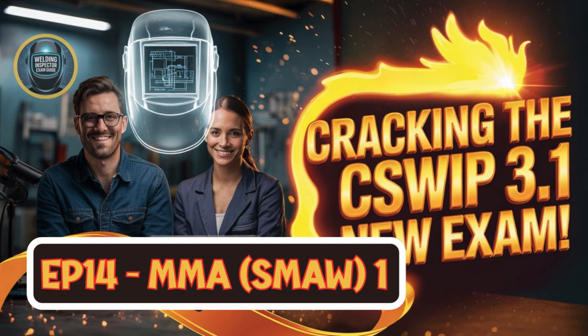Wow, only that much. What happens the rest of the time? The rest of the time is spent on all those necessary but non-welding activities. Stopping to change electrodes every few minutes, chipping off that solidified slag after each pass, maybe grinding out little imperfections or preparing for the next pass, repositioning themselves, repositioning the workpiece. It all adds up. And how does that compare to other processes? Well, you compare that to semi-automatic processes like MIG-MAG or gas metal arc welding. There, the wire feeds continuously. There's often less slag or none. The operating factor can easily be 50%, 60%, even higher in some setups. Double the arc time. Easily double. And then you look at fully automated or robotic welding, where it can be upwards of 90%.